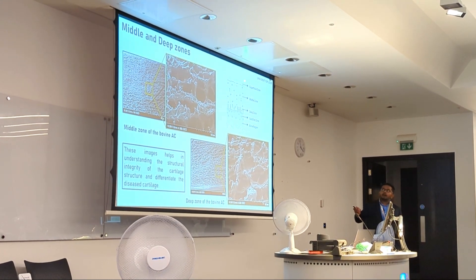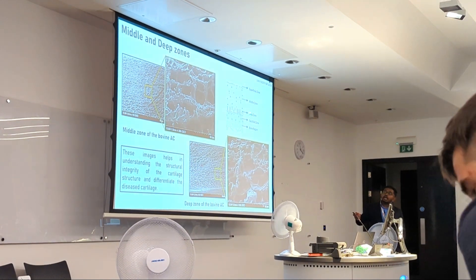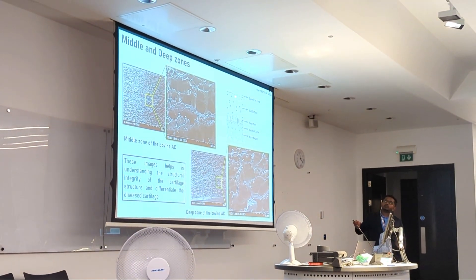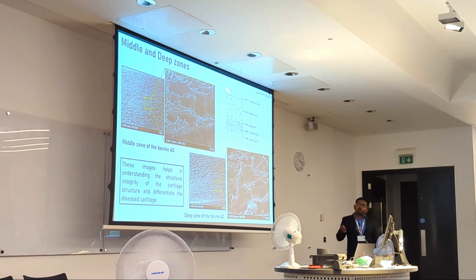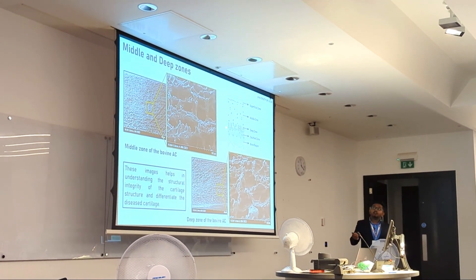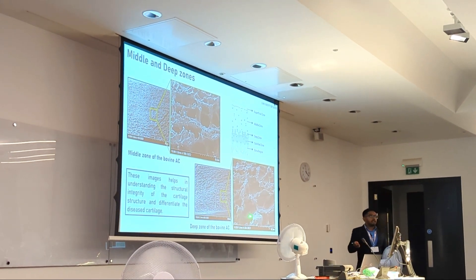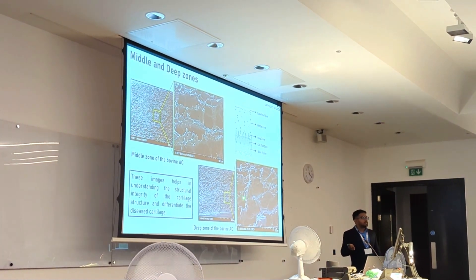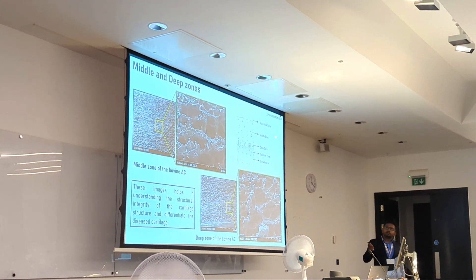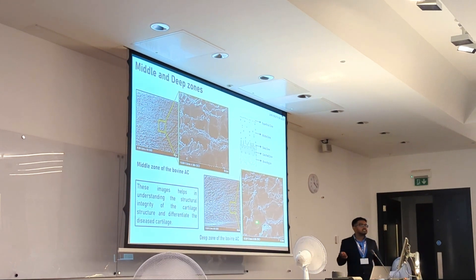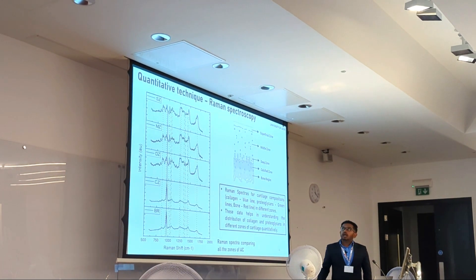The amount of collagen fibrils decreases from superficial to deep zone — meaning the superficial zone has the highest collagen content, decreasing toward the deep zone. Proteoglycans show the opposite trend: lower at the superficial zone and increasing toward the deep zone. To understand how these zones degenerate, we must study the cellular lacunae structure, as that is where proteoglycans are located. In osteoarthritis, the main component that degrades is the proteoglycan.